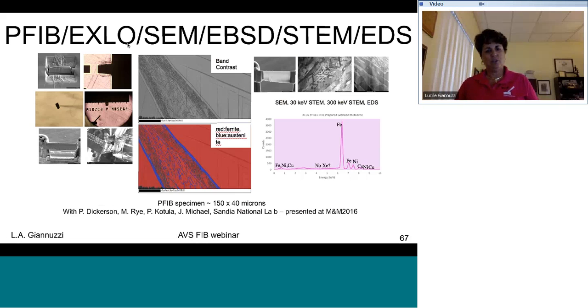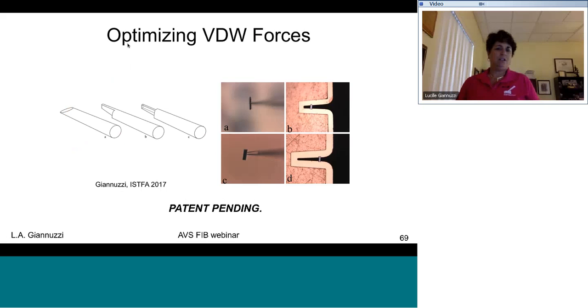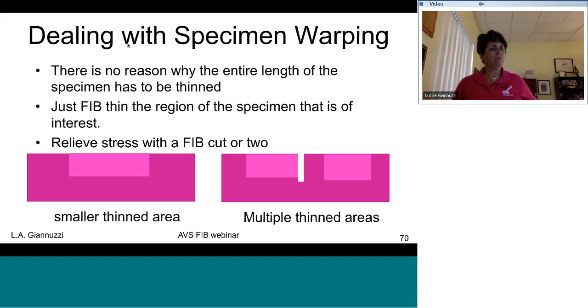And this was the work that I showed early on. A large sample lifted out, placed on the grid, in this case using N-bond glue as well, but there's your EBSD and STEM analysis. And you can also optimize the van der Waals forces by making larger flat surfaces. Okay, so just some generic stuff, how to deal with specimen warping.